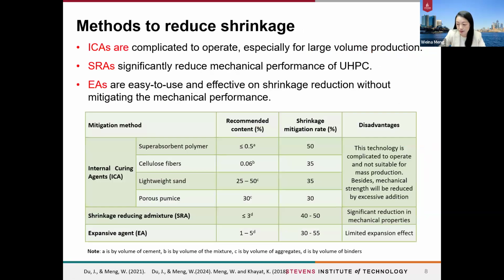To address the first issue, the high cracking potential, the most effective way is to reduce the shrinkage of UHPC. So properly use the internal curing agents, shrinkage reducing admixtures, or the expansive agents. This shows a comparable shrinkage mitigation rate, as summarized in this table. However, using the internal curing agents, usually we will need at least 24 to 48 hours to pre-saturate these types of materials, and that is identified as not very practical.